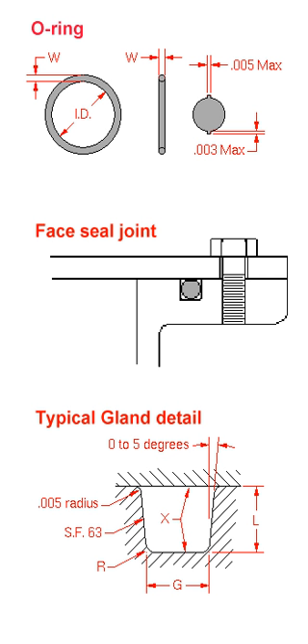There are O-ring materials which can tolerate temperatures as low as −200°C or as high as 250°C. At the low end, nearly all engineering materials become rigid and fail to seal. At the high end, the materials often burn or decompose. Chemical attack can degrade the material, start brittle cracks, or cause it to swell. For example, NBR seals can crack when exposed to ozone gas at very low concentrations unless protected. Swelling by contact with a low viscosity fluid causes an increase in dimensions and lowers tensile strength. Other failures can be caused by using the wrong size ring for a specific recess, which may cause extrusion of the rubber. Elastomers are sensitive to ionizing radiation; more penetrating radiation such as neutrons may cause rapid deterioration. In such environments, soft metal seals are used.